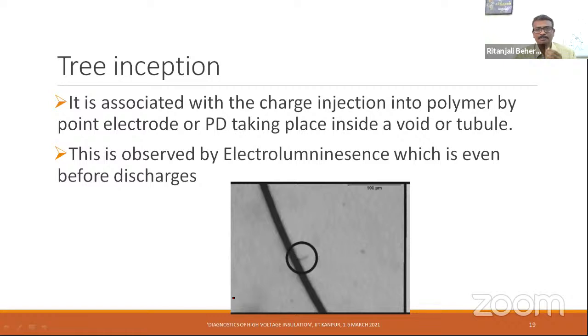Tree inception can be associated with electroluminescence. It was observed by researchers that tree initiation was noted only by electroluminescence, not by partial discharge at that time. So this was once an indication that the first branch or initial branches of the tree had started.